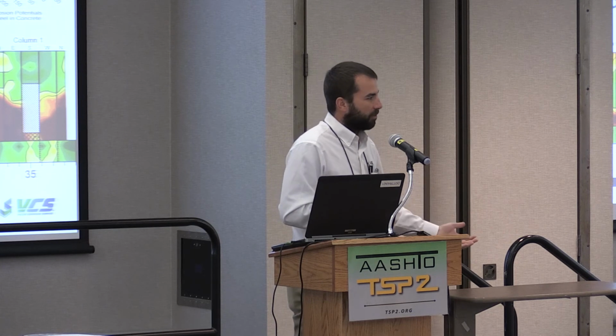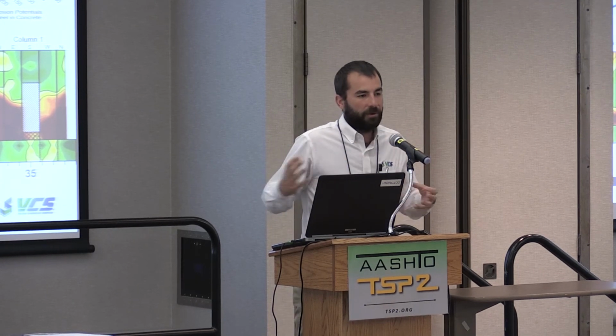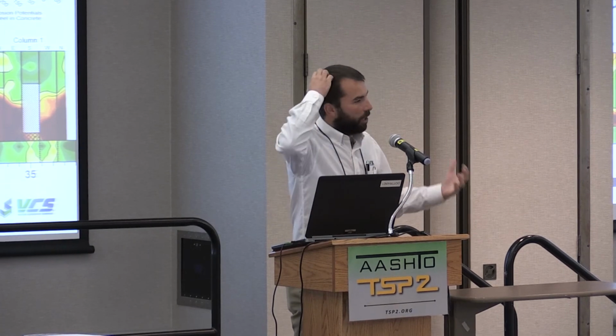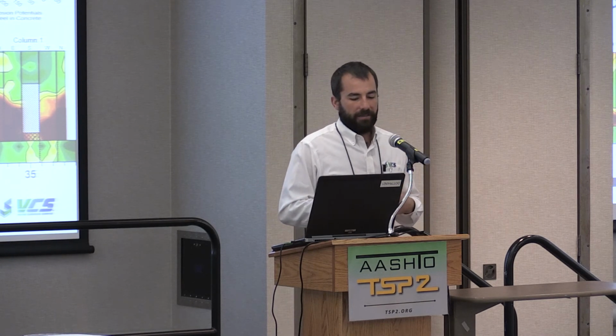And the level of preventative measures, I think, comes down to the owner's past experiences and what kind of budget they're working with. Some owners might say, well, I've got money to spend elsewhere, I can't afford to work on something that's not corroding today, so they may skip this part. I would say at the very least, moisture is going to be the enemy here. Can we put a silane or something on the footer to help keep it drier? We have high chlorides there, but if we can limit the moisture content, even with high chlorides, we'd limit the corrosion rate.